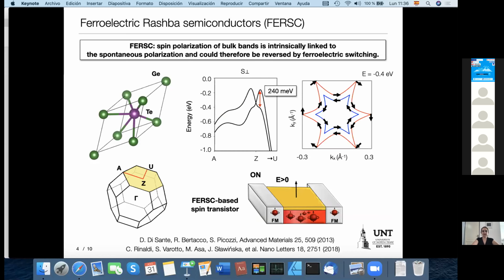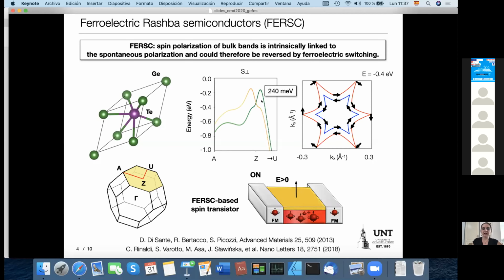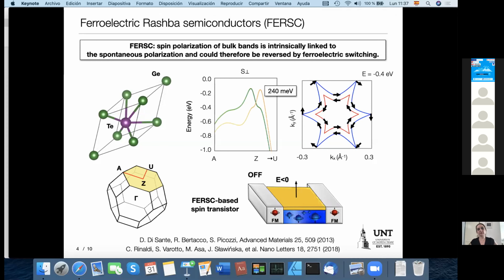Ferroelectric Rashba semiconductors were proposed a couple of years ago, theoretically. The concept itself is not so complicated. We have a ferroelectric, so we have a polar distortion, which intrinsically breaks the inversion symmetry in this material. And due to the symmetry breaking, we have splitting of the bands. In germanium telluride, the splitting is quite large. Of course, we also have spin texture. And what is really interesting about this material is that when we switch to the opposite distortion, for example, by applying the electric field along this axis, we can also switch the spin texture. So we have the link between the polar degrees of freedom and spin degrees of freedom.